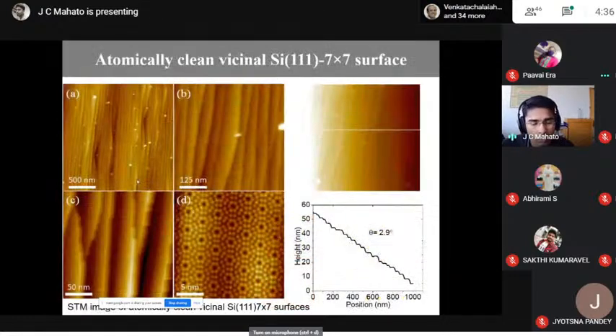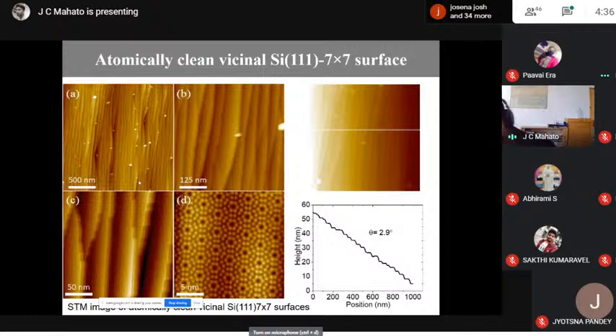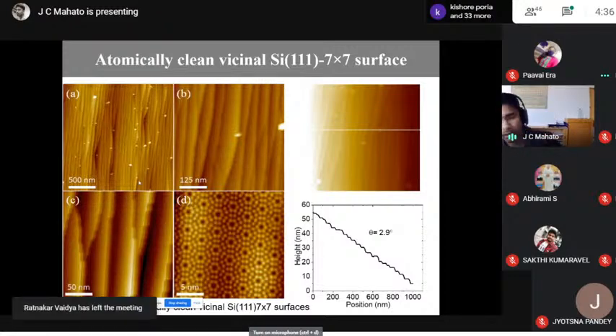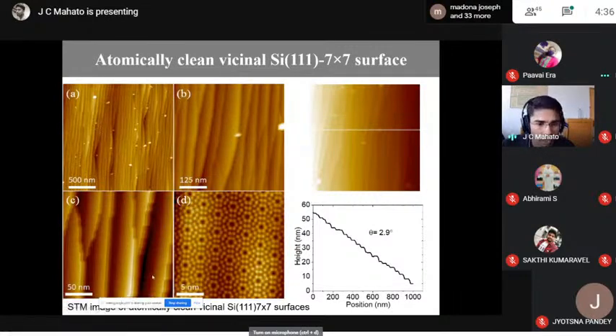So we have taken a vicinal surface. Vicinal surface means that the offcut angle is higher. So here we chose 3 plus minus 0.1 degree offcut angle. So this is a large area STM image of the atomically clean silicon surface, and this is a closed view. And here we can see the atomically clean flat top surface where the atoms are arranged regularly. This is one 7 by 7 surface unit cell. We have taken a line profile. From that we found that the surface offcut is nearly 2.9, that is 3 or 2.9 degrees.